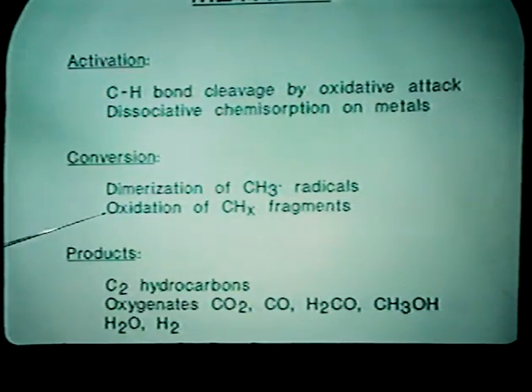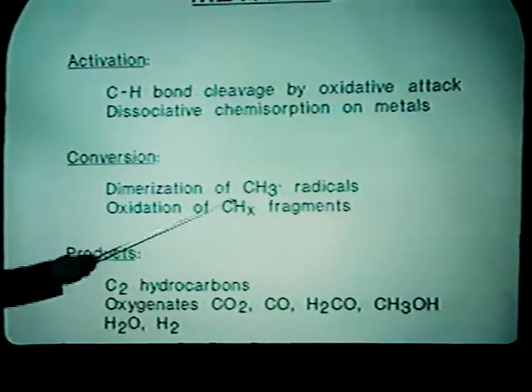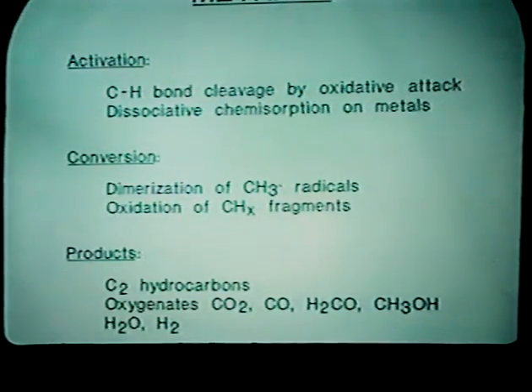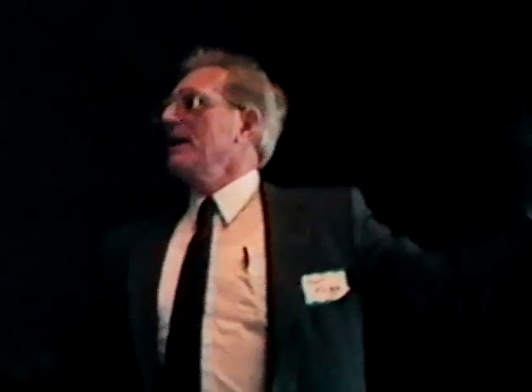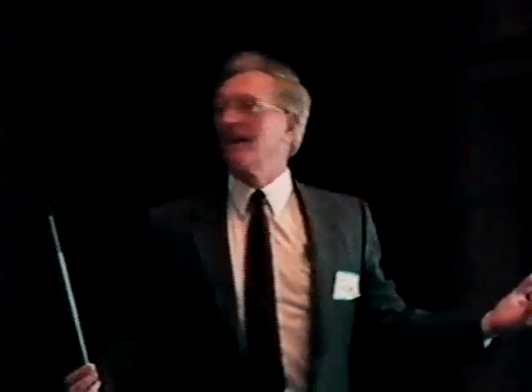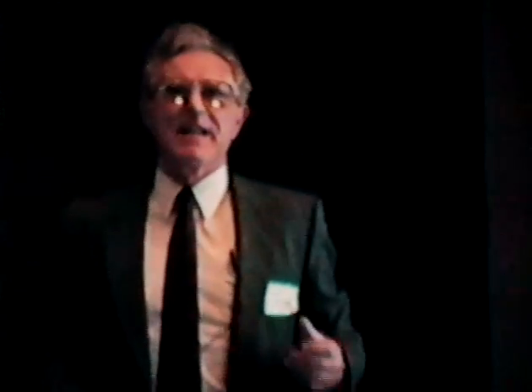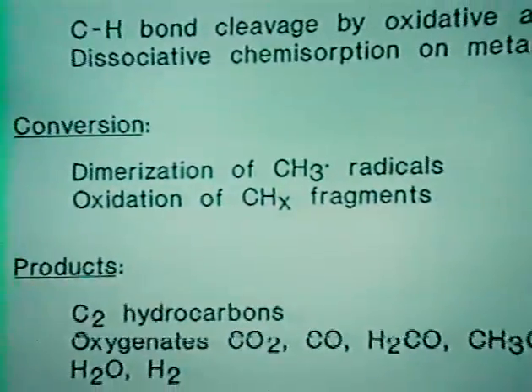And that could be oxidation of CHx fragments, and in fact single crystal work has shown that you can, under certain conditions, keep CH3 fragments or CH2 fragments, a CH fragment, and atomic carbon or agglomerated amorphous carbon or graphitic carbon. I view the contribution of the single crystal surface science to be in providing us with that detail, even though in practical catalysts we don't use all that detailed information. We pick only that which is convenient.